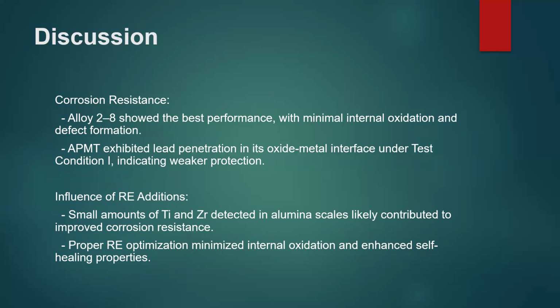APMT exhibited lead penetration at its oxide-metal interface under test condition 1, indicating weaker protection. Regarding the influence of RE addition, small amounts of Ti and Zr detected in alumina scales likely contribute to improved corrosion resistance.